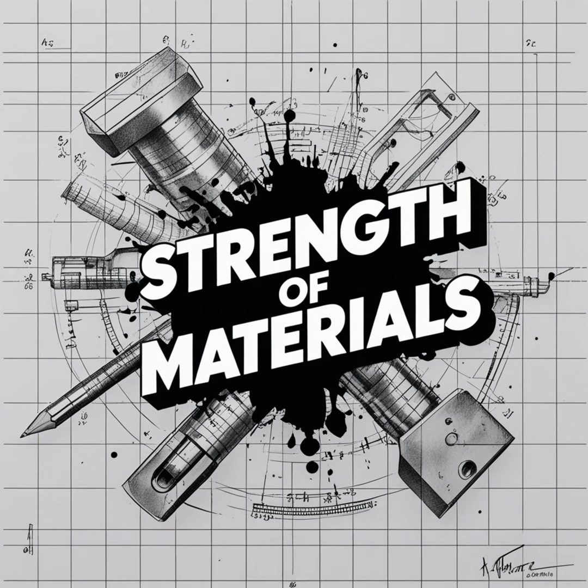It does not. And this phenomenon is an absolute lifesaver for civilization. For many materials, specifically most plain carbon steels and titanium alloys, as you drop the stress lower and lower, the SN curve eventually flattens out entirely. It becomes a perfectly horizontal line. And what do we call that? This threshold is called the endurance limit or the fatigue limit.